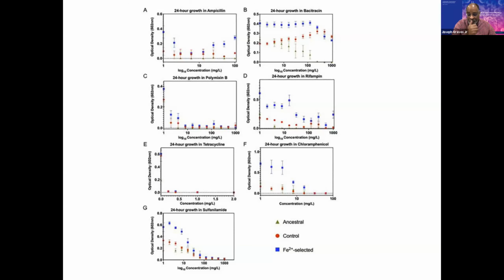Now, we've also shown in a paper that's under review right now in Nanomaterials using magnetite nanoparticles. Magnetite is a composition of both iron 2 and iron 3, that the same thing happens. So when we produce magnetite resistant bacteria, okay, they become resistant to iron 2, iron 3, gallium, okay, they have some minor silver resistance, and also all of the same antibiotic resistances that we show here occur in magnetite resistance. So this was, again, an unanticipated result of these experiments.